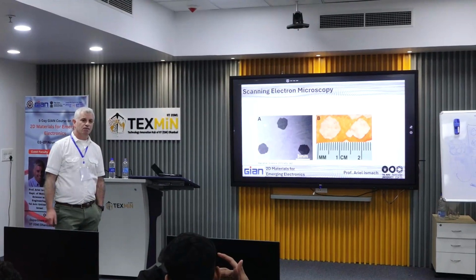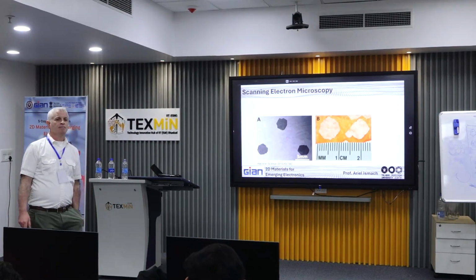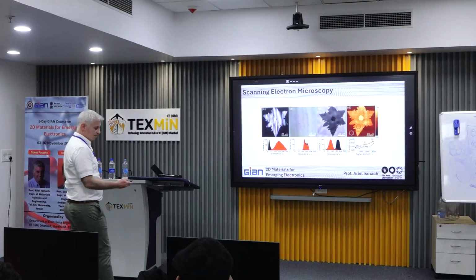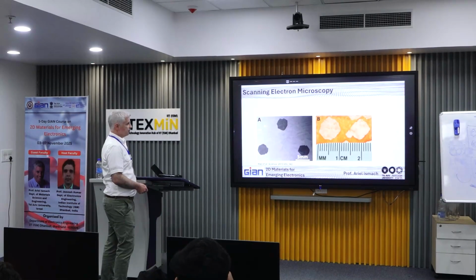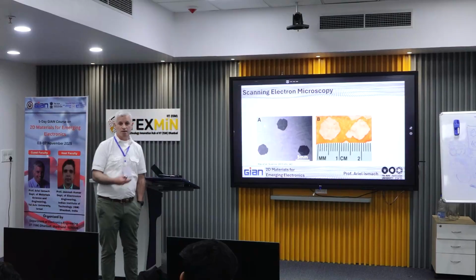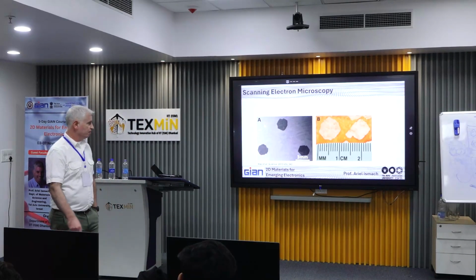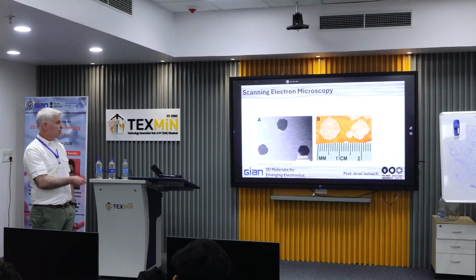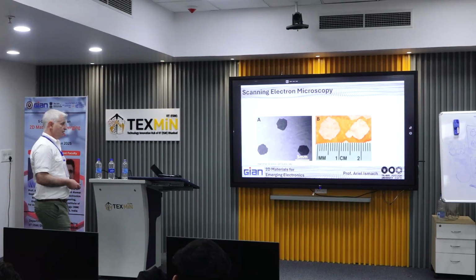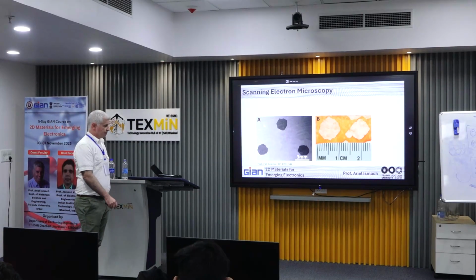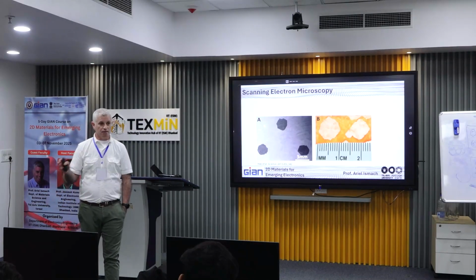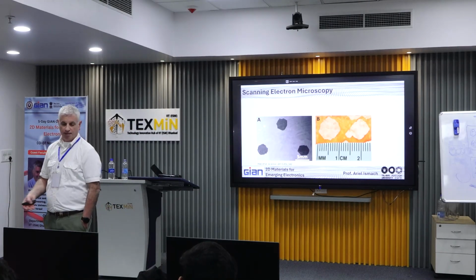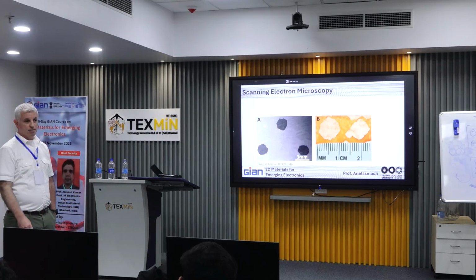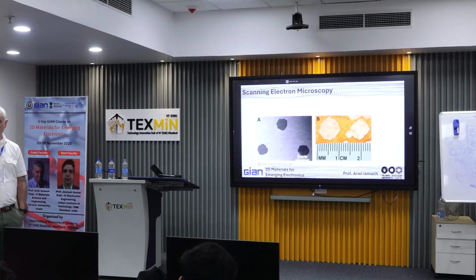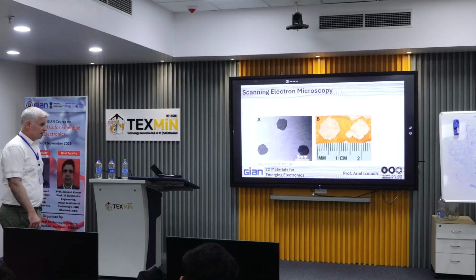But the copper is a very good conductor. But it also comes from the oxide. The oxide, yeah, this is the reason. We have an oxide, even an oxide that we don't see in the optical microscope is enough to allow for the big contrast. And of course, if you put the graphene on top of a silicon dioxide substrate, you will also see a huge contrast. So even though you have a single atomic layer, it's very easy to see this in SEM.